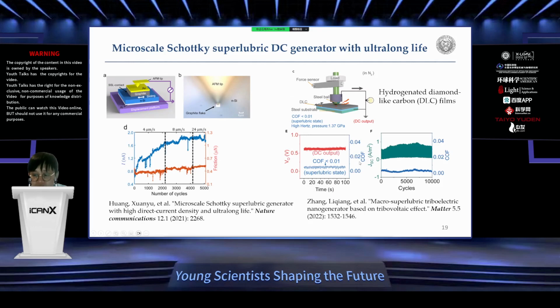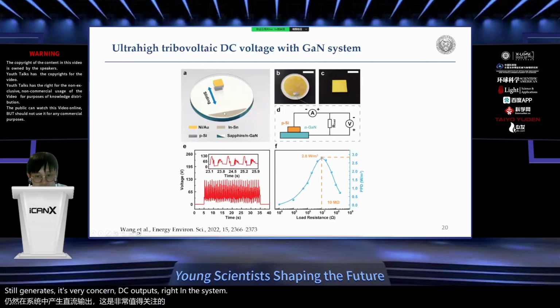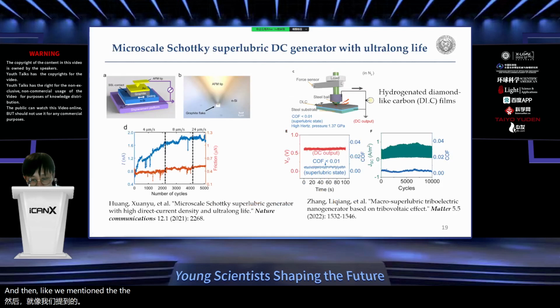Also, there's a recent work here using hydrogenated diamond-like carbon films rubbing on silicon substrates, and they have done even 10,000 cycles. Different from the first paper, this is actually a macroscopic demonstration. At the same time, they measured the coefficient of friction, which is less than 0.01, very low friction, but they can still generate very constant DC outputs in this system.